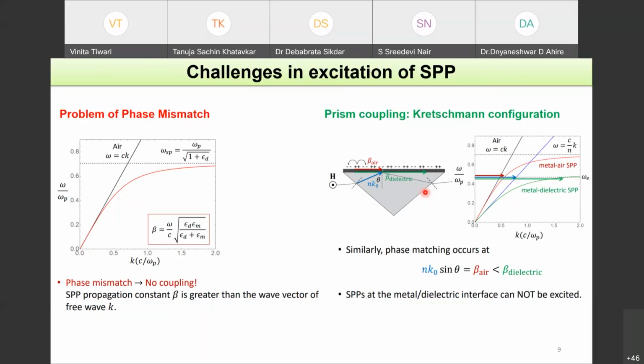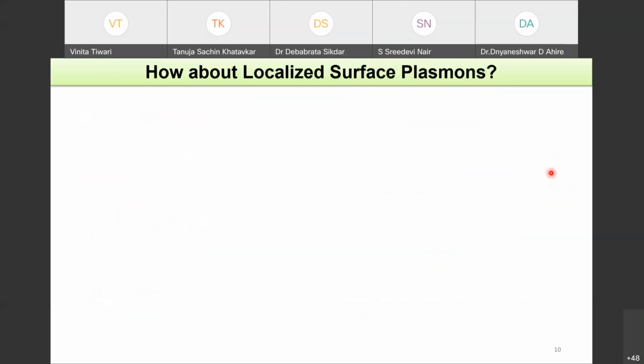But will you be able to do it at the metal dielectric interface? Because here there are basically two interfaces. One is metal dielectric, another is metal air interface. If you look at this equation, this curve is the dispersion relation for the metal dielectric SPP. You will not be able to couple this photon to this plasmon, because all of these already have much higher momentum than your photons. So coupling of SPPs at the metal dielectric interface is not possible, but you will be able to excite surface plasmon polaritons at the metal air interface. That is doable. So as you can understand, exciting SPPs at metal dielectric or metal air interface is a bit tricky. So how about localized surface plasmon?